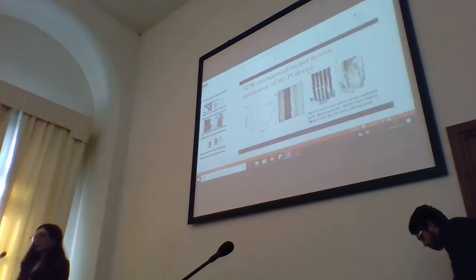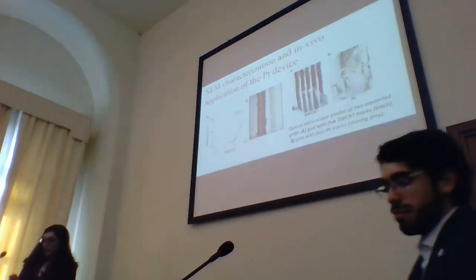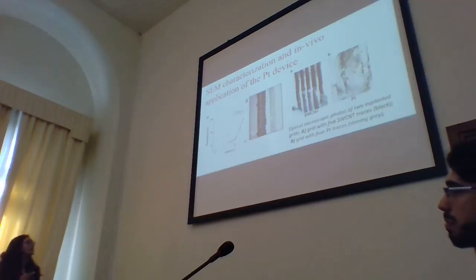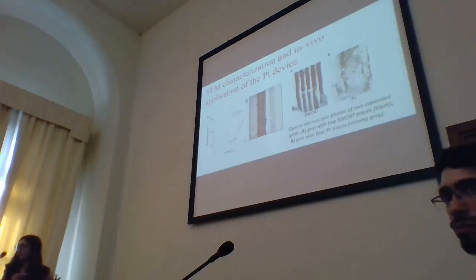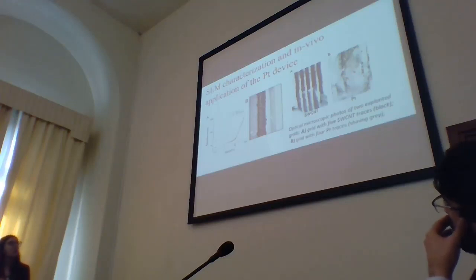As I told before, we have also made the device with platinum, but as we can see in the first image, the difference is that after stretching the device, the resistance of the carbon nanotube tracks increases only with a bigger stretch, while the resistance of the platinum track increases for a little time, but then the track is broken. And these are two images of the device of carbon nanotube and platinum after the explantation.